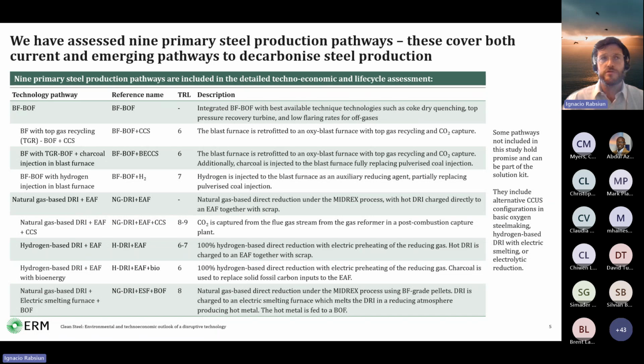But in terms of basic oxygen steelmaking, other than the conventional unabated pathway, we considered retrofitting carbon capture and storage to the blast furnace, combined with a modification of the blast furnace with top gas recycling to become an oxy blast furnace. The same pathway, but where charcoal is used to replace pulverized coal injection into the blast furnace, and then a pathway where hydrogen is injected into the blast furnace.